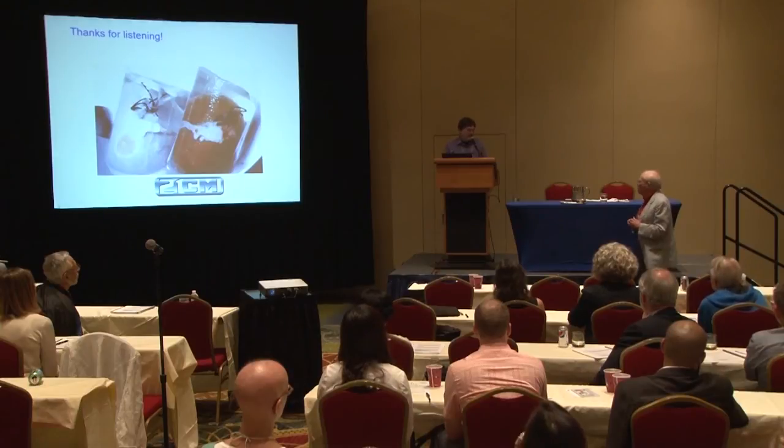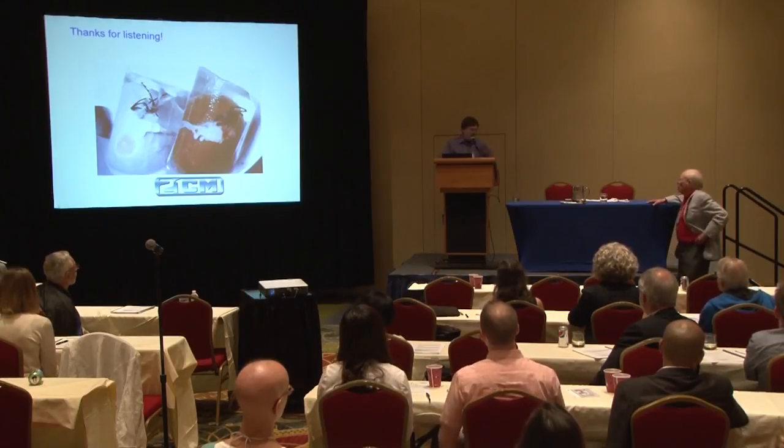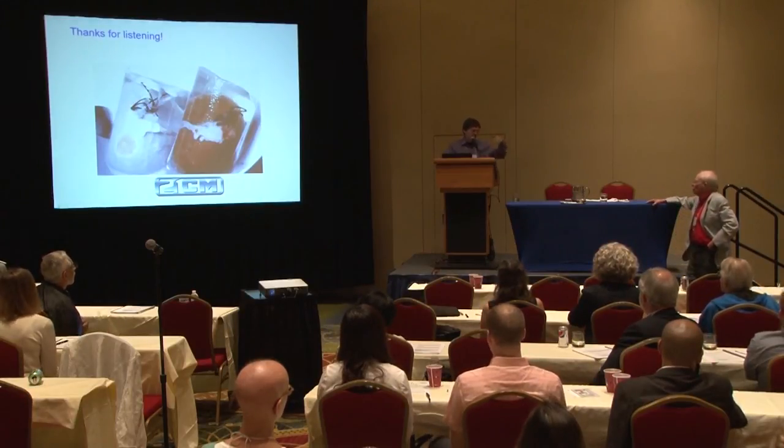Yeah, sure. I was inspired ultimately at the root of all of this by John Farrant, who came up with that idea a long time ago, 1965. It was a phenomenal concept and result that he published in Nature, showing he could take a whole organ, a guinea pig uterus, down to dry ice temperature and back and have it recover fully because he avoided all ice formation in the system. But he had to use multiple steps of DMSO. He used DMSO, which is too toxic to just use outright.